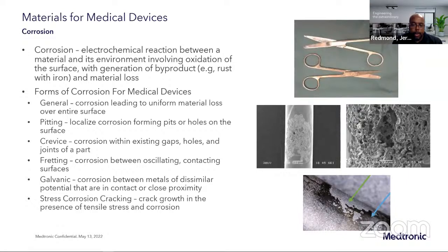If I'm putting in multiple components that are made of different materials, if these materials have dissimilar galvanic potentials within that medium, they can create essentially a circuit between those materials, where there's an electrical path. One material acts as an anode, the other acts as a cathode, and you can have a corrosion reaction where the anode is stripped of its material. And it can be a pretty aggressive attack if the materials are very dissimilar. And so we have to really pay attention to make sure that the galvanic potential of these materials is pretty similar so we don't have that behavior take place.